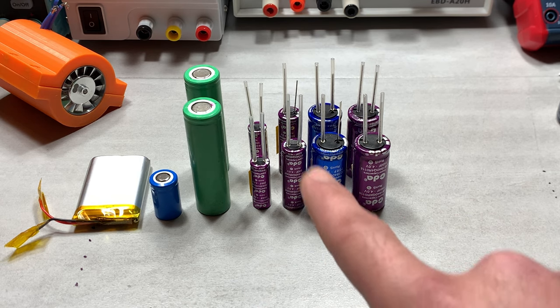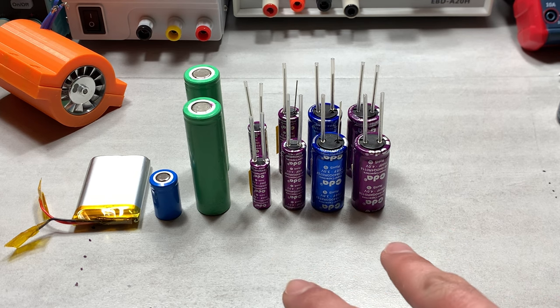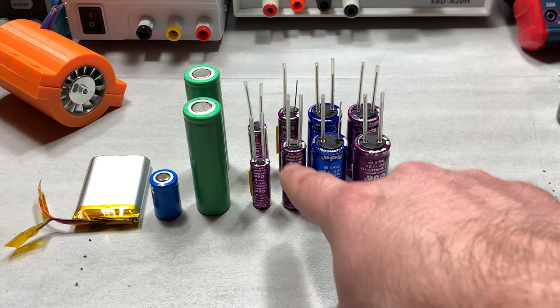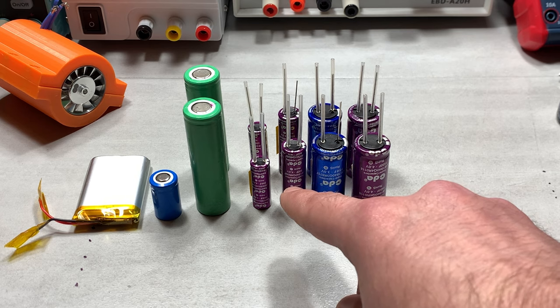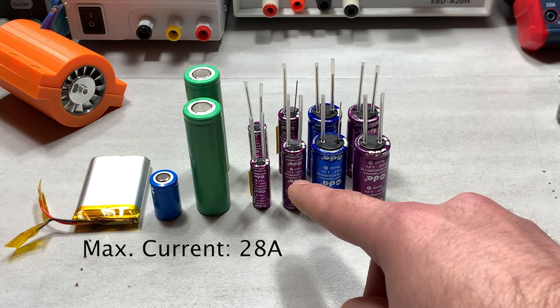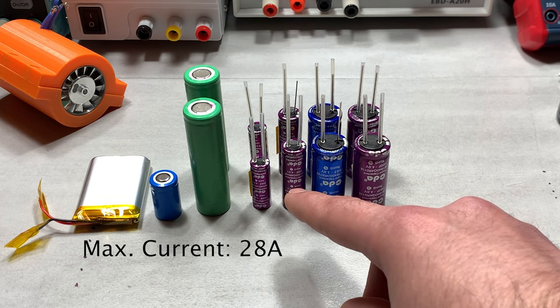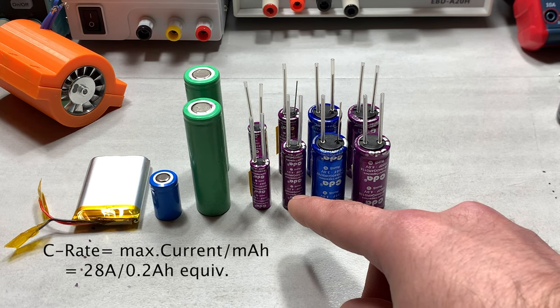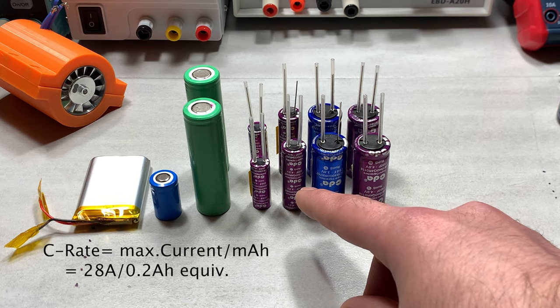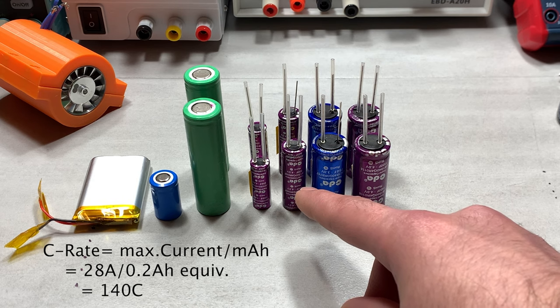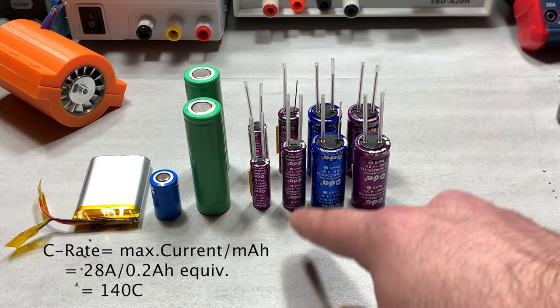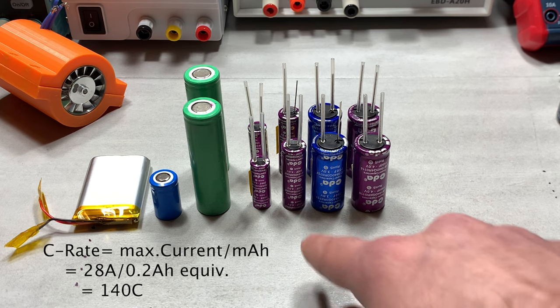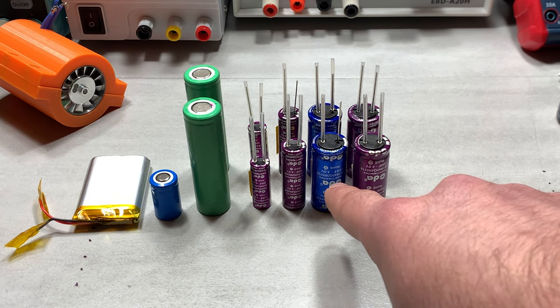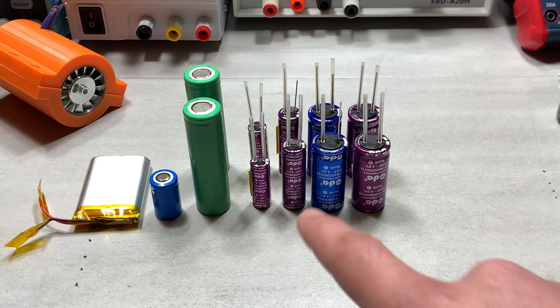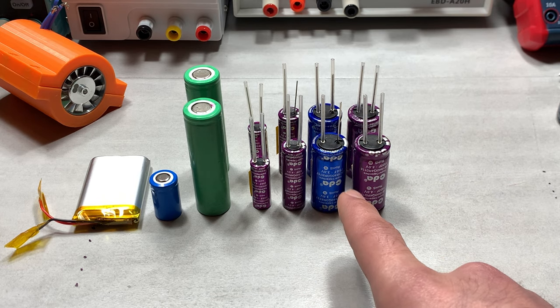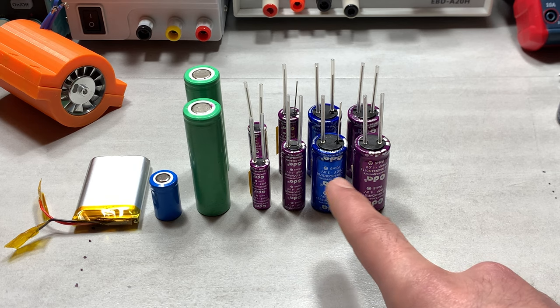And that's only the recommended operating current. The maximum current for this 500 farad 4 volt capacitor is an absolutely insane 28 amps per cell. So just dividing that 28 by 0.2 amp-hours, that gives us a C rating of 140C. That is very, very crazy. So next, moving up to the 750 farad 3.8 volt cell. These are of the LIC type, as the product code says.